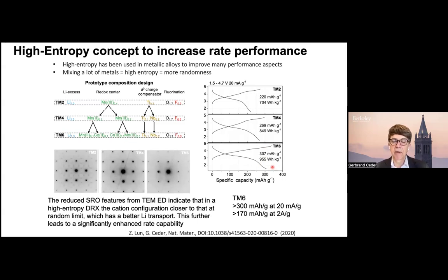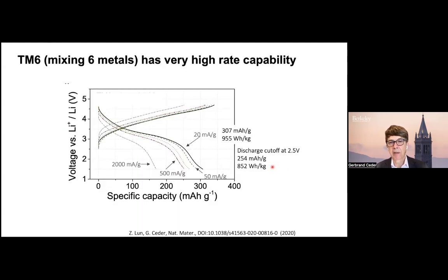So clearly this is evidence that controlling the short-range order improves the rate capability and thereby improves the amount of capacity you can get at a certain rate. And actually, by the time you're at 6 metals, you can do respectable discharge rates, right? So these are experiments where we charge and discharge at different rates. And even at 500 milliamperes per gram, we get quite respectable discharge capacity in these materials.